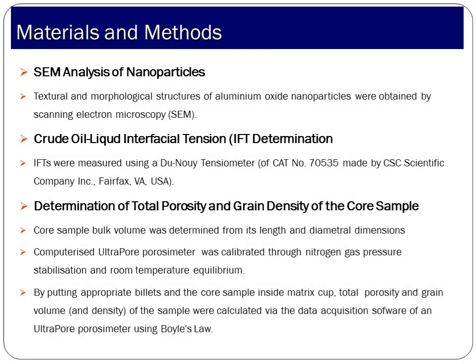Also, scanning electron microscope analysis of the nanoparticles was carried out, and crude oil interfacial tension, IFT, was determined using a tensiometer. Also, determination of total porosity and grain density of the core sample was carried out using a computerized ultra-pore porosimeter, where appropriate billets and the core sample were put inside the chamber to determine the total porosity and grain volume and density of the sample via the software of the porosimeter.